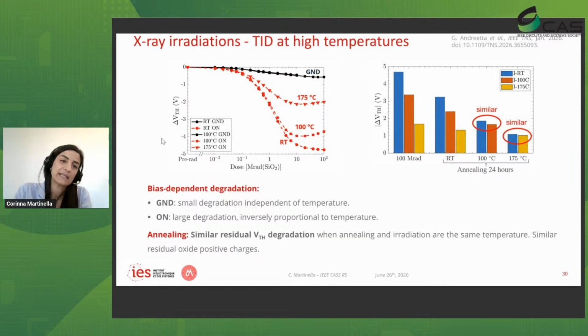Once again, by looking at the delta of the threshold voltage, we can compare results for devices that were irradiated in ground condition, at room temperature, or at 100 degrees C, and in on state. So by looking at the black line, we are seeing the results in ground conditions. In ground condition, there is not so much going on. The degradation is low, and so there is not a big difference when irradiating at room temperature or at 100 degrees C, and so the two lines overlap.